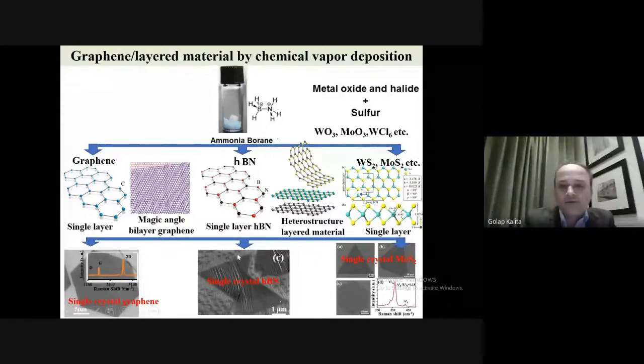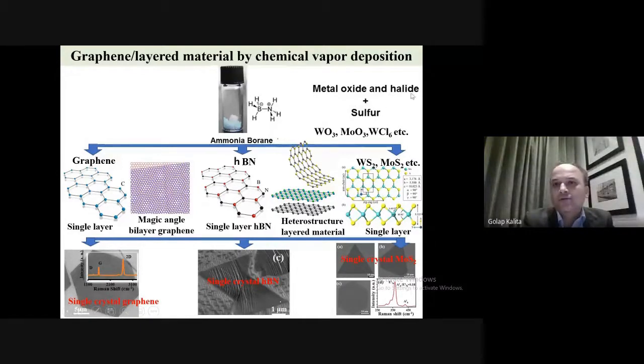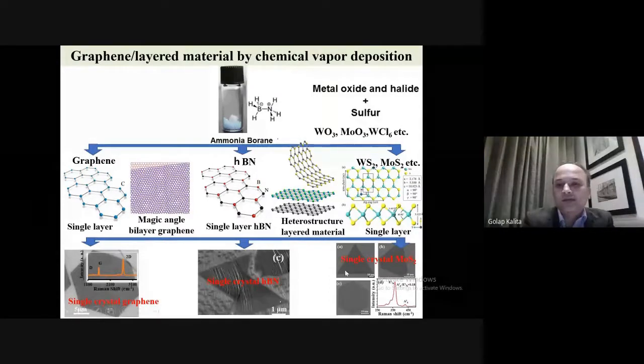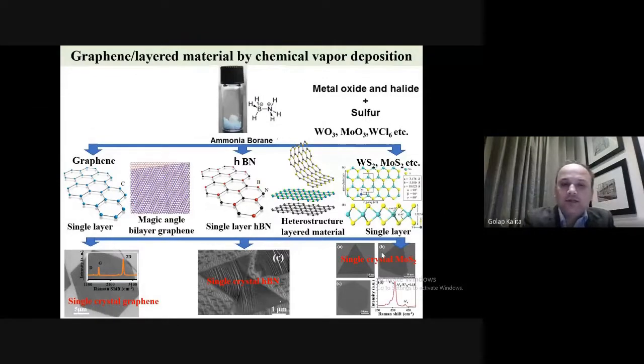Now, there are other studies going on heterostructures of these layers. You can combine an HBN layer, a graphene layer, or MoS2 layers to form heterostructures of this layered material. For chalcogenides, what we do is use metal oxide or halide precursors combined with sulfur. We do a CVD process to get this type of triangular or hexagonal single crystal of MoS2. So this is about a CVD process, where we synthesize single layer graphene crystal, HBN crystal, or MoS2 crystals.